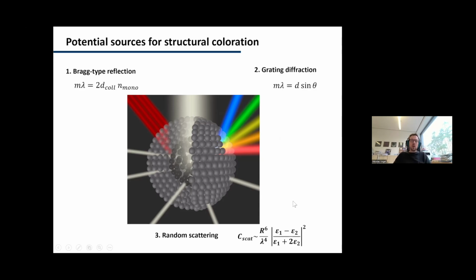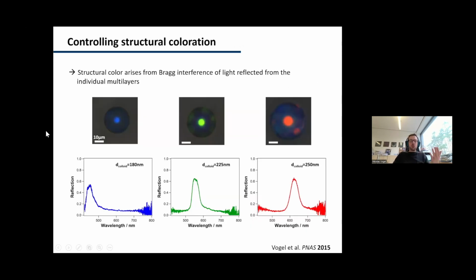So how can we now leverage these things to actually make structural color pigments? The first thing is we can change the size of the particles. By this, we change the conditions for constructive interference. And this allows us to make structurally colored materials all the way through the visible spectrum. So from blue via green to red, and if we want, we could also make them smaller or bigger or in between. So this shows us that we can really not only mimic the colors in nature, but tune the colors the way we like.